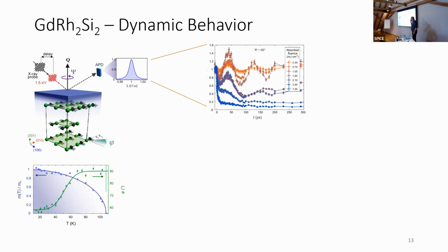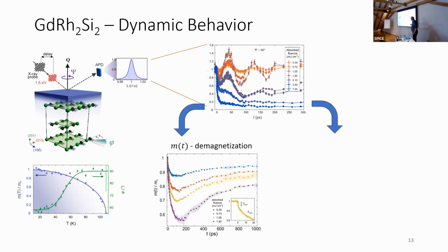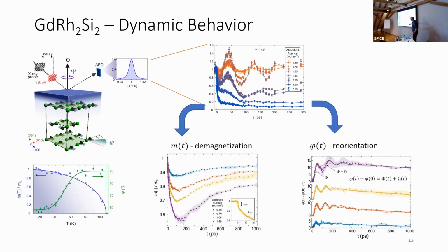To my knowledge, this is the first time that azimuthal dependence is measured in the time domain. And what you can see here is that a lot more is happening than just a weakening of the order parameter or just a rotation. There's some sort of superposition of both effects. And with a lot of details that I won't go into, we disentangle the two effects that are seen here. One of them is demagnetization and recovery, this blue line here, when it's static. And here, what you see is the coherent rotation of the entire spin structure.